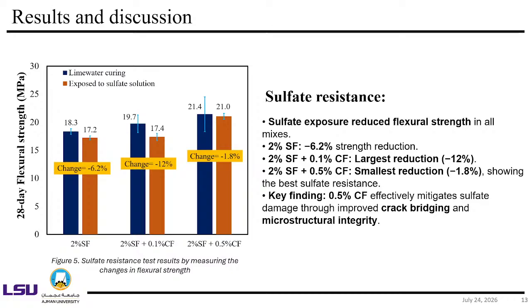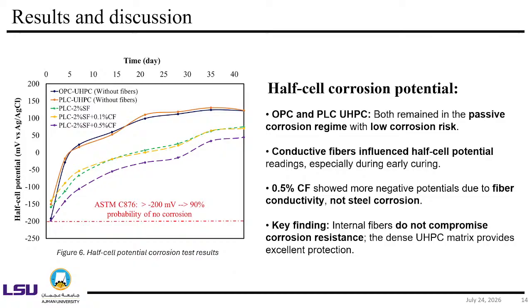Next is the sulfate resistance. For sulfate resistance, we tested the flexural strength after 28 days of exposure in sulfate solutions. The orange data is after the exposure, and lime water curing you can consider as normal curing. There is a decrease after sulfate exposure, which is expected. However, the one with the most carbon fiber has the least reduction, which is again very good. The 0.5% carbon fiber samples have improved crack bridging and microstructure integrity, and therefore the least reduction in sulfate resistance.